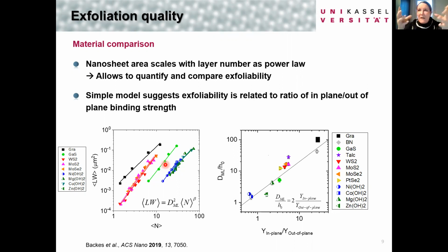When we imagine this, we have these 2 processes occurring with an equipartition of energy, where the energy that goes in goes equally into both processes. You can understand why you don't have large and thin sheets, because large sheets would have overall a larger interaction between the sheets. So you need more energy to exfoliate them, but this energy also goes into breaking the sheets. This is the idea behind the model.